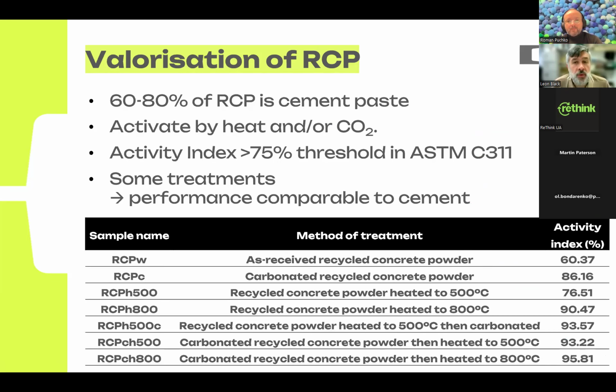So we looked at this material that was 80% cement paste. I've seen other samples anything between 60 and 80%. And we activated it by either heat and or carbon dioxide. Okay, heating drives off the water and can ultimately lead to some phase changes. Adding carbon dioxide